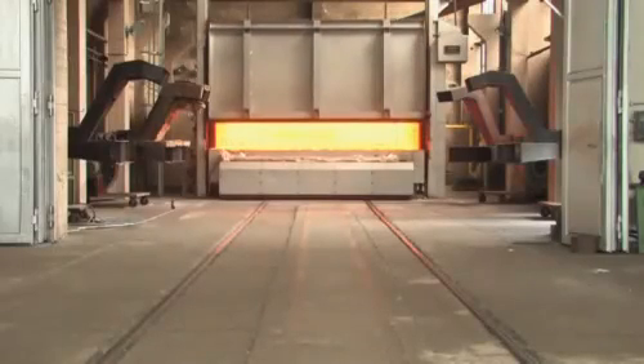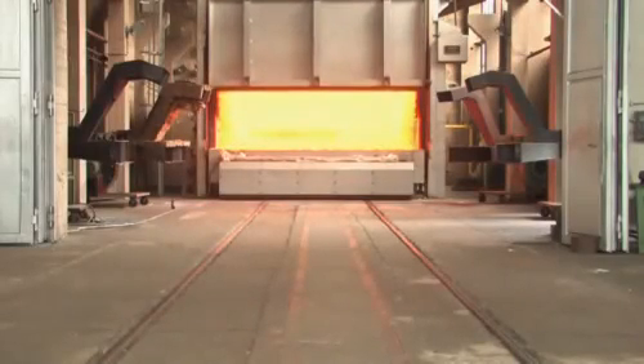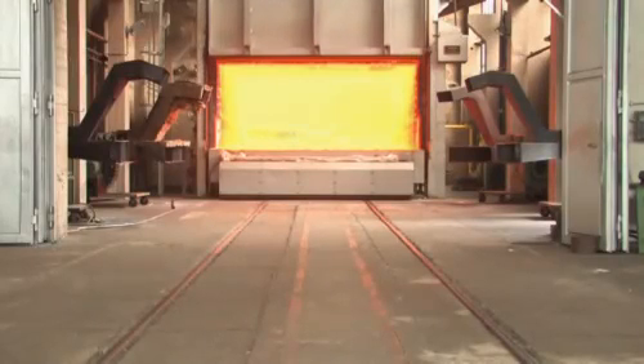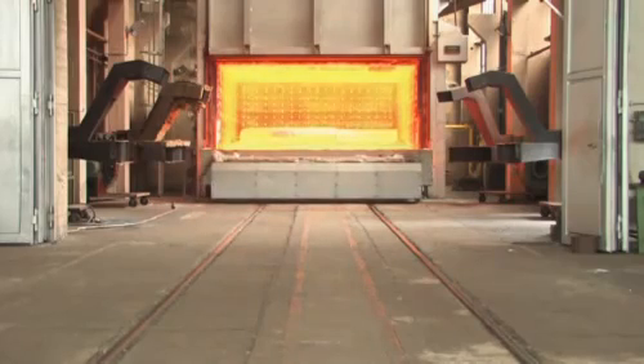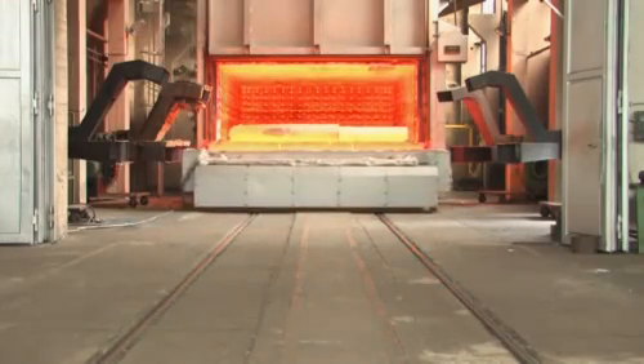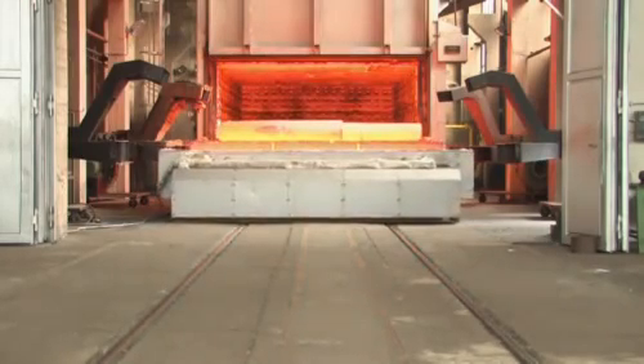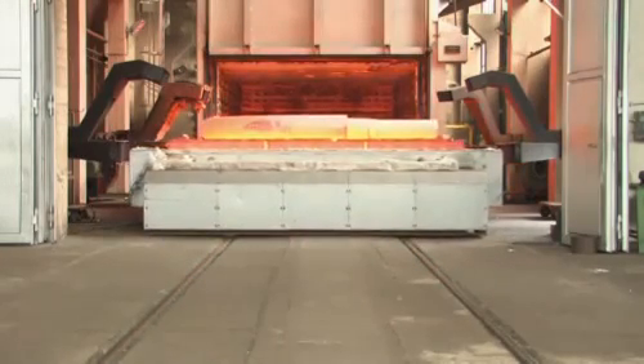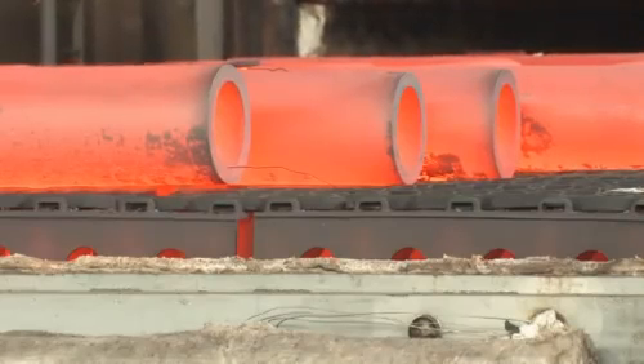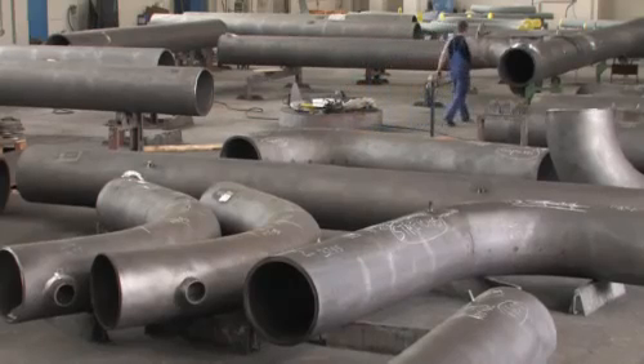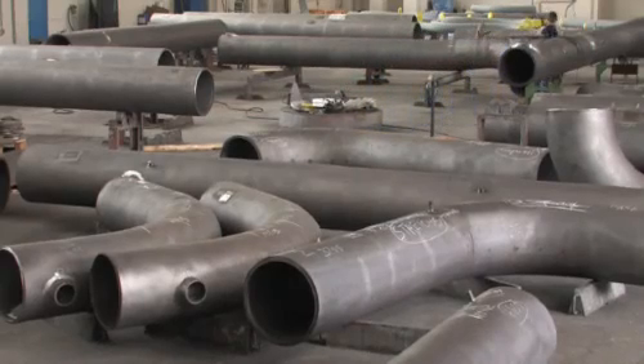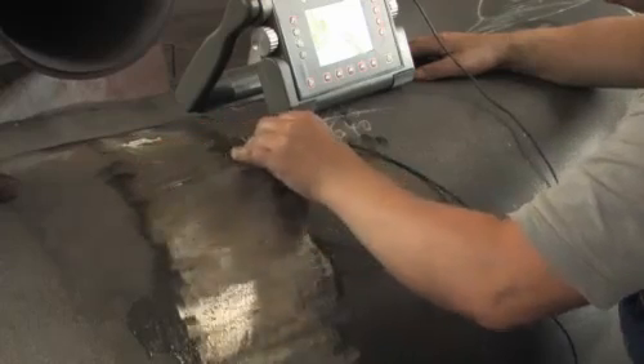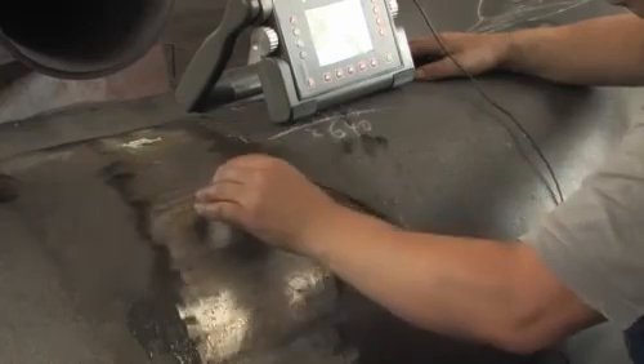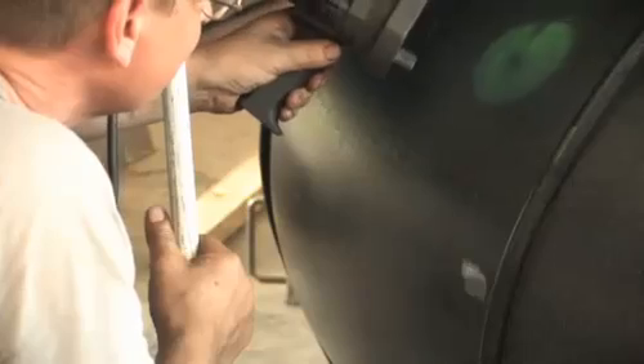Depending on the material type and wall thickness, the pipe is heat-treated after its bending in the annealing furnace. The annealing parameters are also strictly specified and precisely recorded. Heat-resistant material is hardened at temperatures higher than 1000 degrees Celsius and subsequently tempered. The boundary dimensions of the bend are exactly measured. The finished spool is examined based on extensive non-destructive examinations. These include ultrasonic wall thickness measurement as well as magnaflux crack testing.